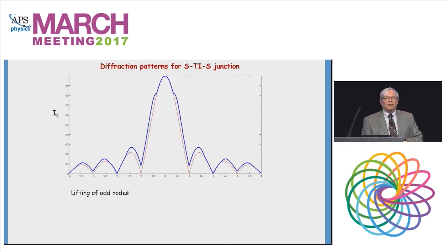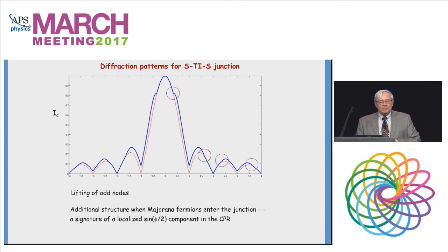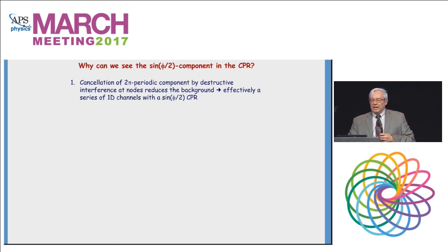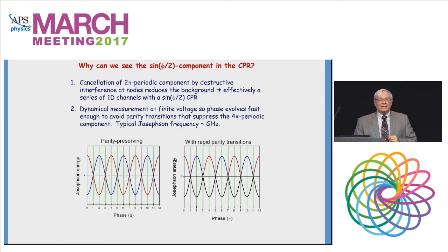If you take that and you calculate the diffraction pattern, you see this pattern I suggested, a lifting of the first node, hard second node, lifting of the third node, and so forth. Okay, so that's some evidence, and so the question becomes, why can we see this? You expect to have parity transitions between states, but we can really see it for 2 reasons. One, we cancel the first order Josephson term, getting rid of a lot of other things in the junction. And secondly, we go very fast, as Cam was pointing out. You have to go fast enough that you keep the parity the same and don't allow parity transitions. You can do that by measuring the diffraction pattern because you're actually biased in a finite voltage state. So even though you're measuring DC voltages, the Josephson frequency is actually in the gigahertz or sometimes even terahertz.